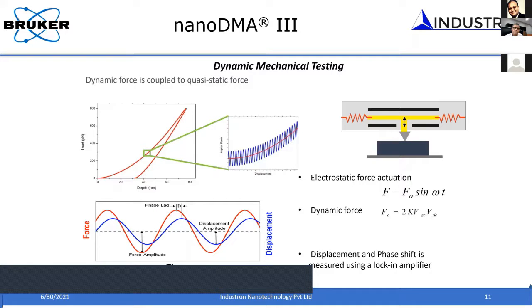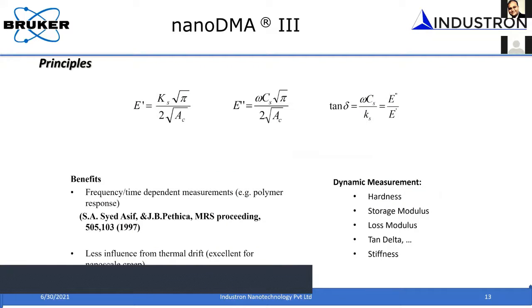That phase shift can be measured using an instrument called a lock-in amplifier. And by measuring this phase shift, along with the known oscillatory force that you are applying and the oscillatory displacement that you are measuring, you can measure the viscoelastic characteristics of the material, namely the loss modulus and storage modulus, tan delta, and many things. Okay, so I'm not going to go through all these details in modeling.